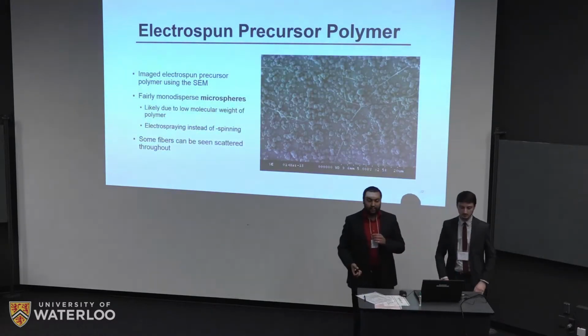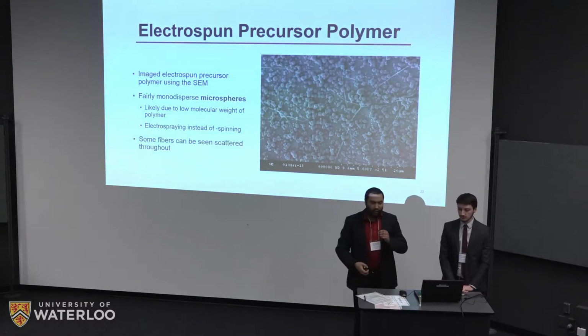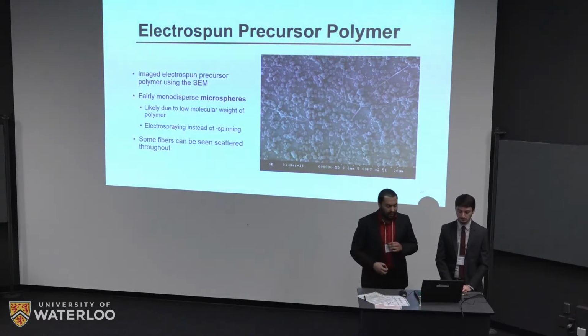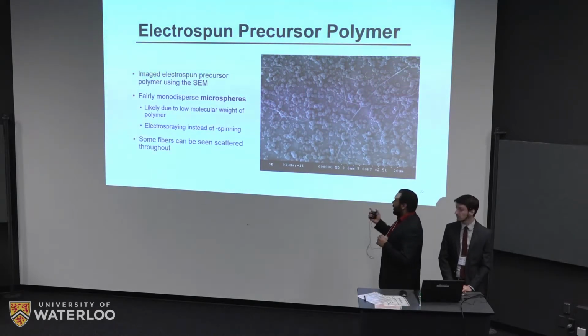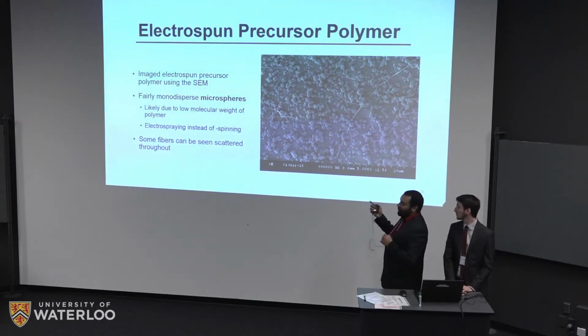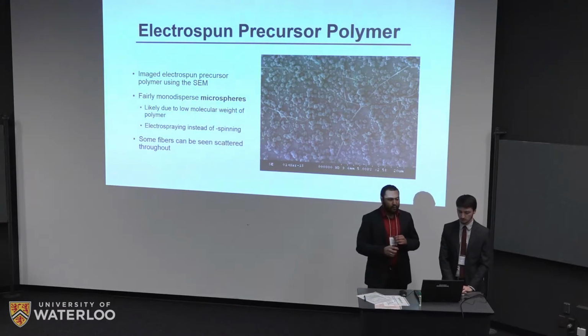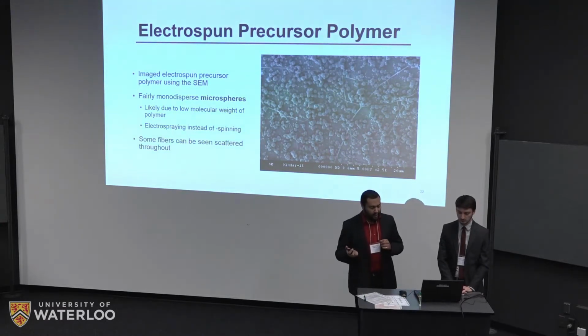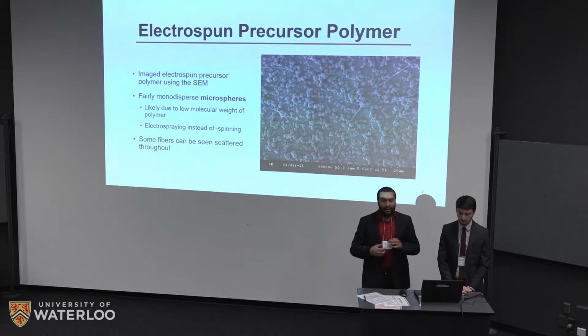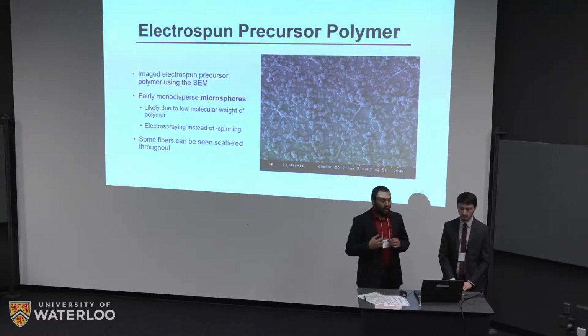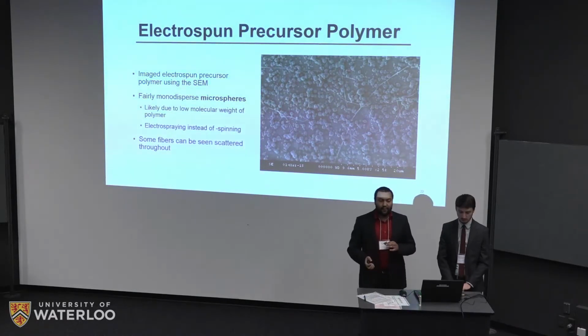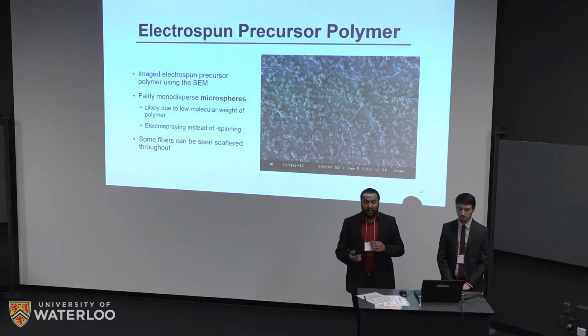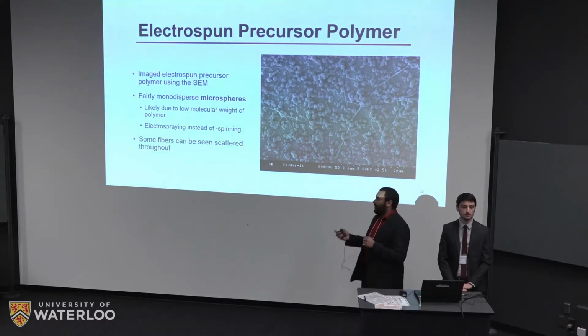After completing some of these validation tests, we decided to electrospin our actual precursor polymer, polyamic acid. You see in the SEM image here, this is what we got. This is a more sparse area of the sample, but we got microspheres instead of fibers. This is actually an artifact of electrospraying instead of electrospinning, the main difference being that the polymer stream breaks apart and instead forms droplets.